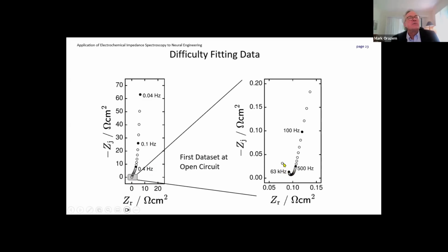But we also see these 2 points over here. These points come because of the transition from a steady state behavior to impedance. Normally, we throw away the first measurement we measure because of this transition from a steady state behavior to the impedance behavior. But in this case, we had to throw away these two. Once we did that, we were able to get good fits to these data.